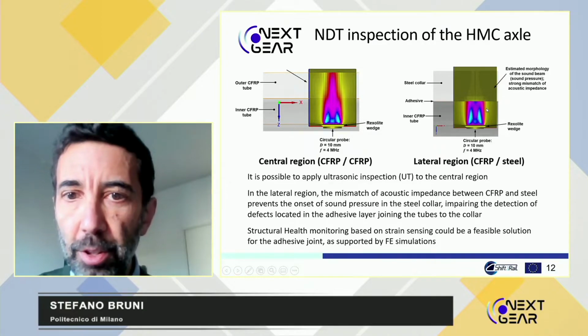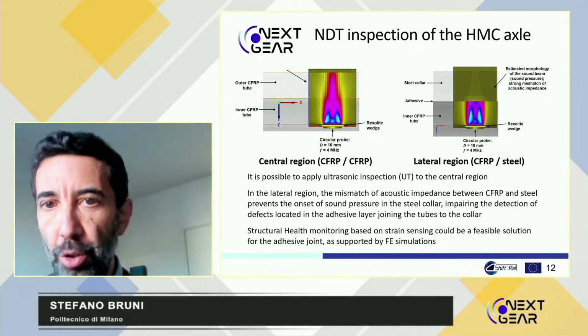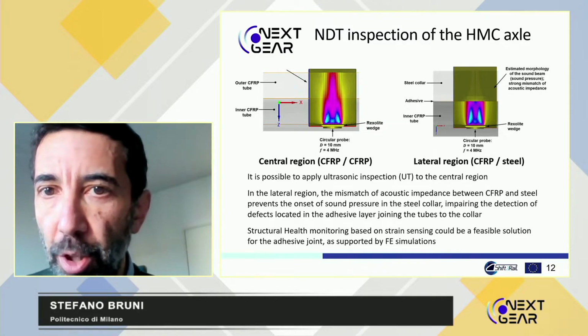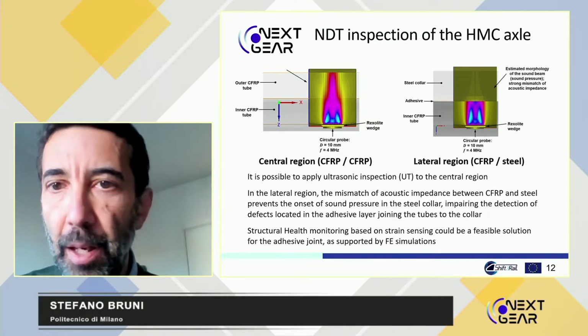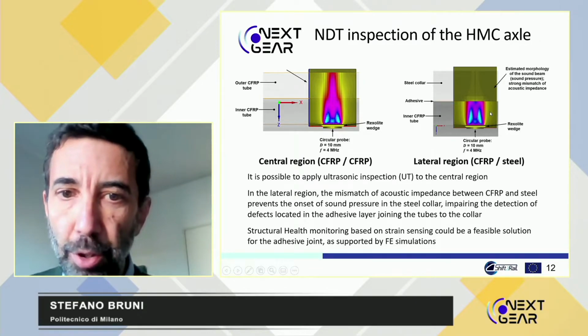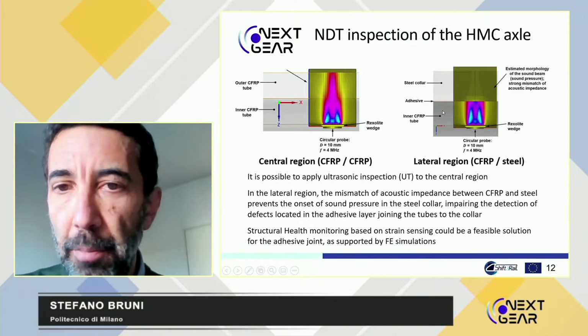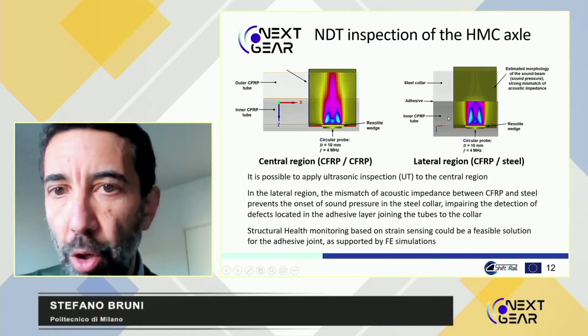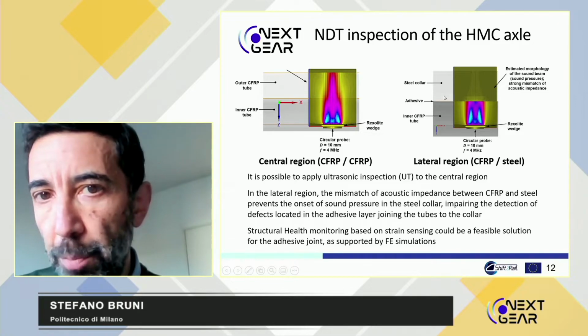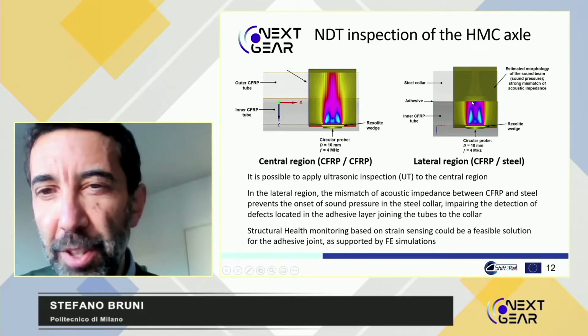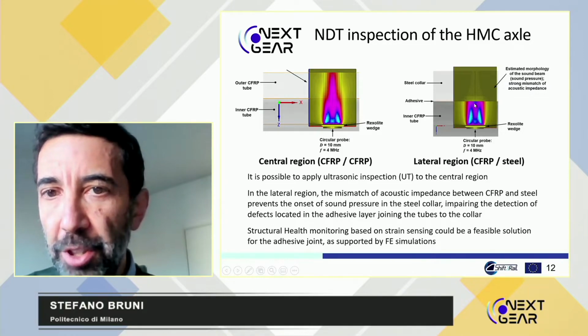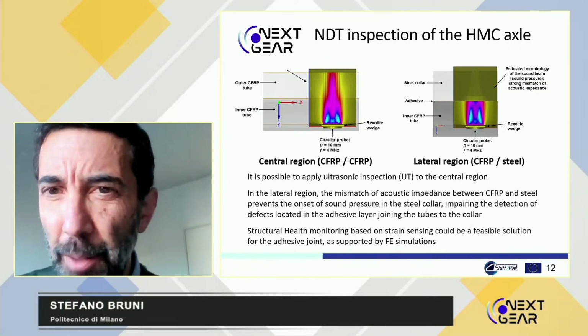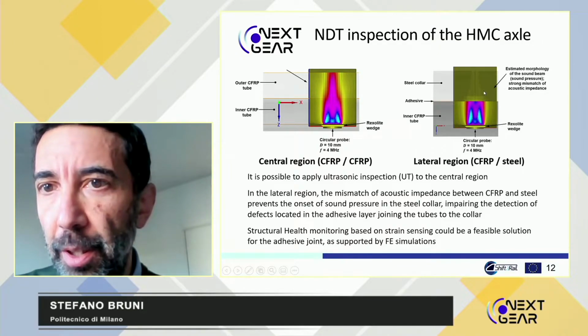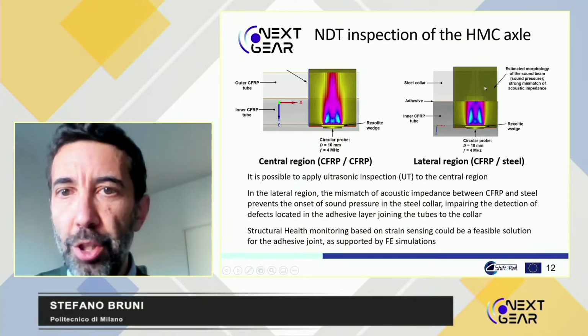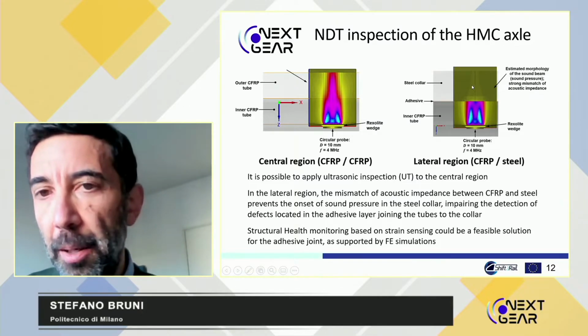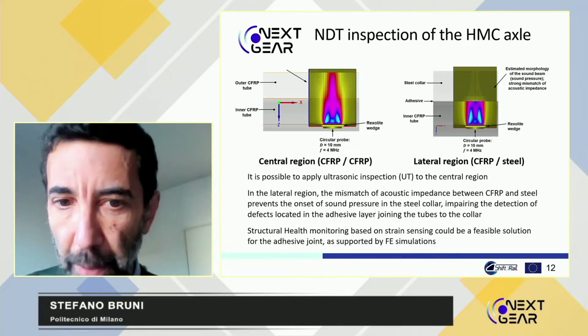When we get into the lateral region of the axle, the portion where we have the outer metallic collars, then we have an important mismatch between the acoustic impedance in the material of the inner portion, the composite tube, and the outer portion, the steel collar. And this basically blocks the ultrasound waves, which means any defect which could be in the outer part could not be seen by this inspection method.